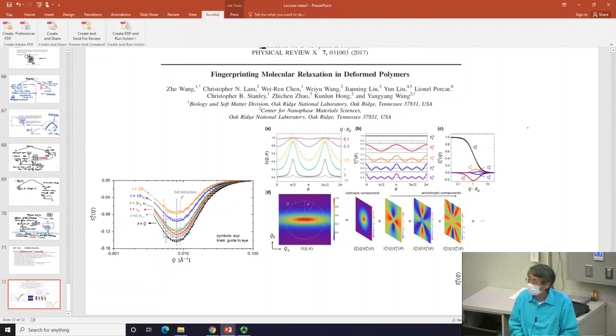In particular, he recognized that one way of analyzing neutron scattering data was to do it as the people who have done it for colloid, which is to treat the raw data directly, looking at the intensity and breaking down the neutron scattering intensity directly in terms of summations of so-called spherical harmonic functions, so that your analysis will not be model dependent per se.